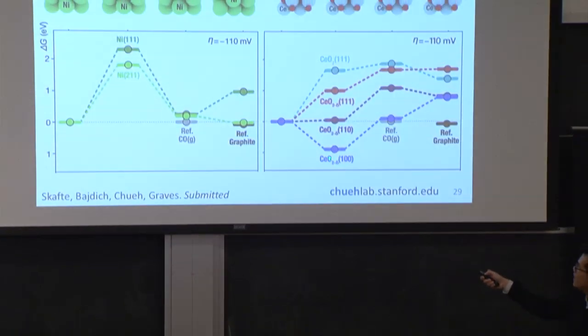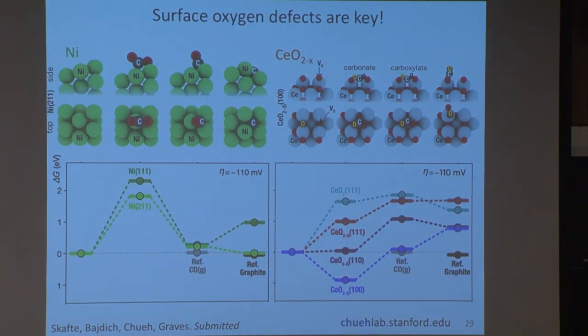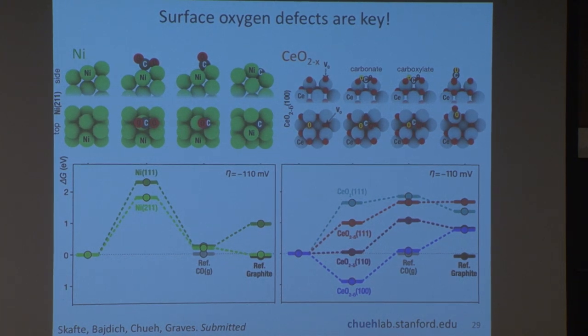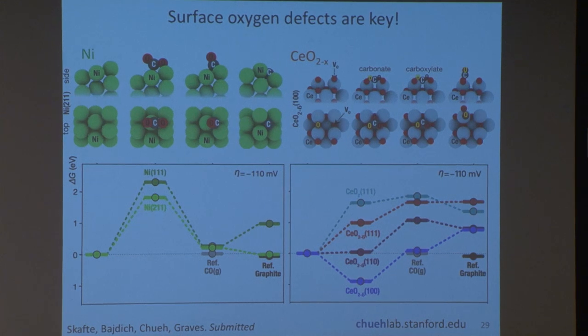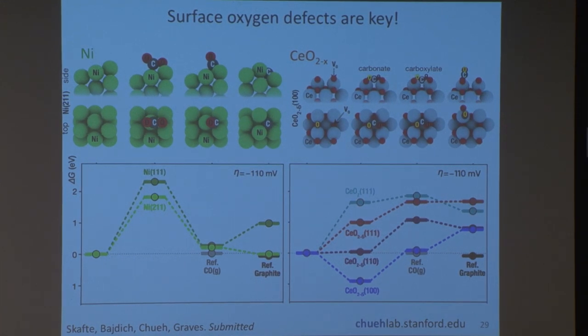And then secondly, you see after you get down here, it's all uphill. It's uphill to make CO, and it's furthermore uphill to make carbon atoms. And the energy barrier you have to pay to turn CO2 into carbon is this 2 steps uphill. And that's nearly 2 electron volts. So this is very challenging. But to make CO, the barrier is only 1 electron volt. So essentially what you're doing here is using an oxygen deficient surface, you coordinate the carbonate adsorbate much better. You stabilize it in contrast to the metal surface because you can't form the bond on nickel. You stabilize that, then you increase the relative barrier going to the carbon product. And this is why we can't deposit carbon on ceria.